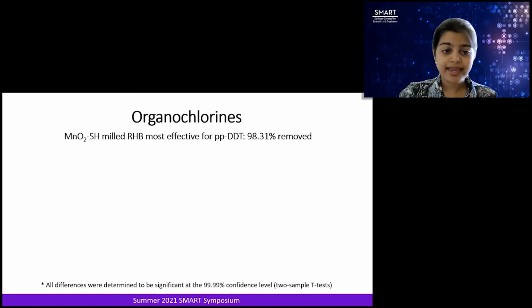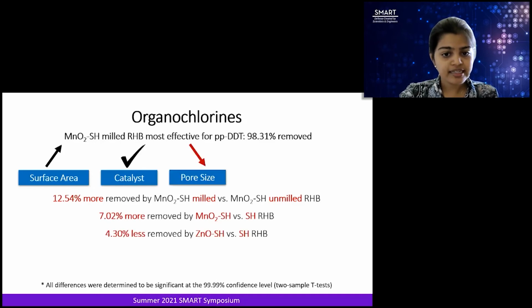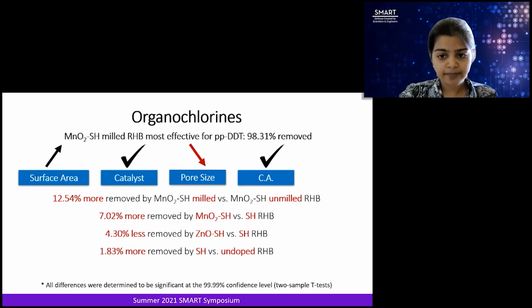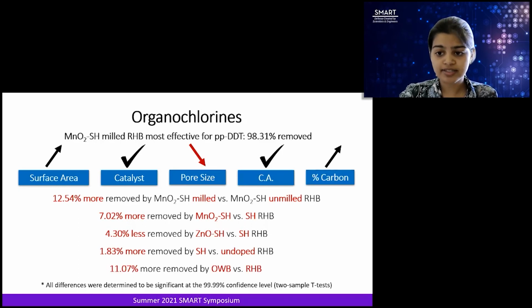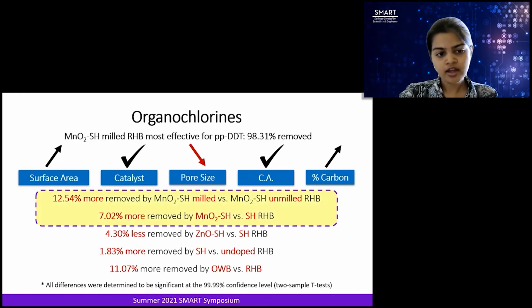For organochlorines, manganese oxide thiol-doped biochar was the most effective, removing 98.31% of PPDDT. This tells us that high surface area, catalyst presence, decreased pore size, complexing agent presence, and increased percent carbon composition are key for contaminant sequestration. Moreover, 12.54% more PPDDT was removed by manganese oxide thiol-doped milled rice husk biochar versus unmilled rice husk biochar, which tells us that high surface area is key for PPDDT removal. Also, catalyst presence is key because 7.02% more PPDDT was removed by manganese oxide thiol-doped biochar versus just thiol-doped biochar.